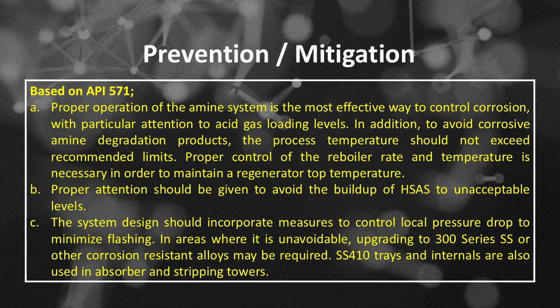Number B, proper attention should be given to avoid the buildup of HSAS to unacceptable levels. Number C, the system design should incorporate measures to control local pressure drop to minimize flashing. In areas where it is unavoidable, upgrading to 300 series SS or other corrosion-resistant alloys may be required. SS410 trays and internals are also used in absorber and stripping towers.